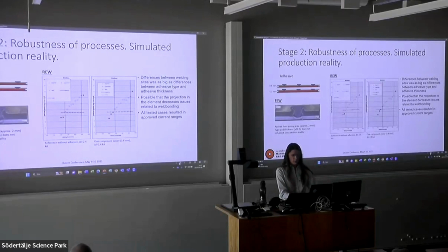Adhesive, we saw that it was possible to join with adhesive. That was not a big problem really. In friction element welding, the adhesive is pushed away from the joining area, and in resistance element welding, we saw bigger differences when the joints were welded on different sites than actually we saw with different adhesive or different adhesive thickness. It is also possible that this little projection in the resistance element could help with contact. So this projection could maybe even facilitate a bit when including an adhesive in the joint, if compared to traditional spot welding.